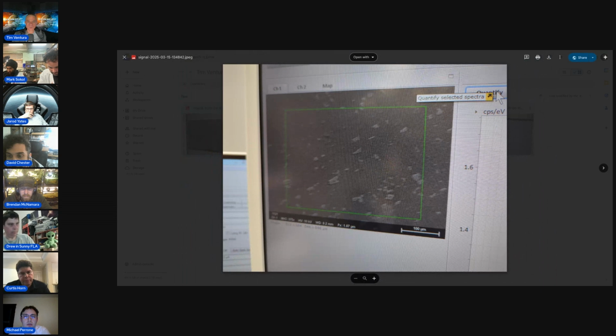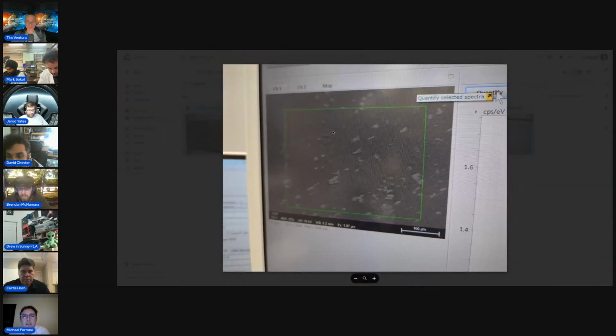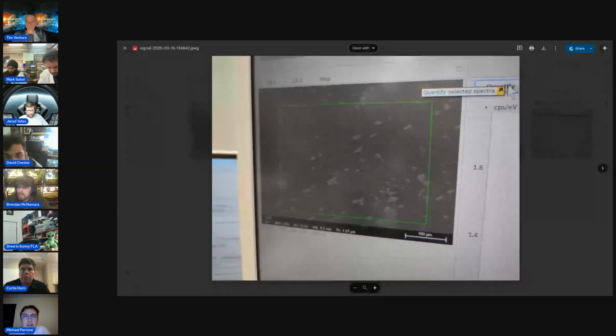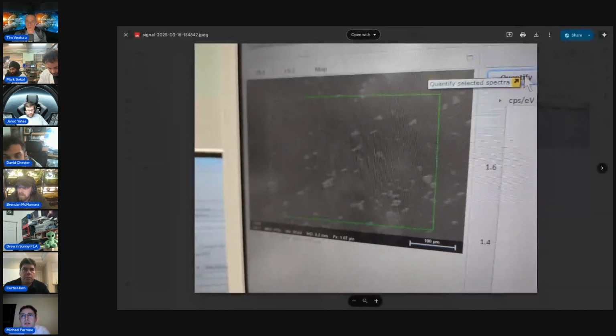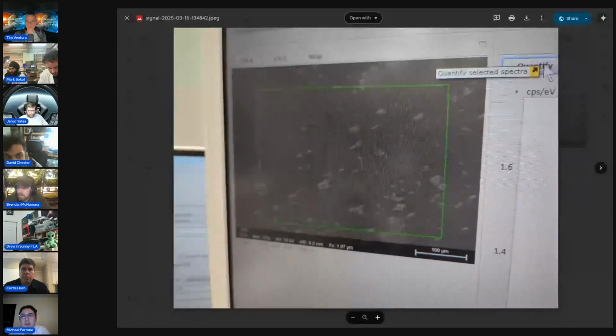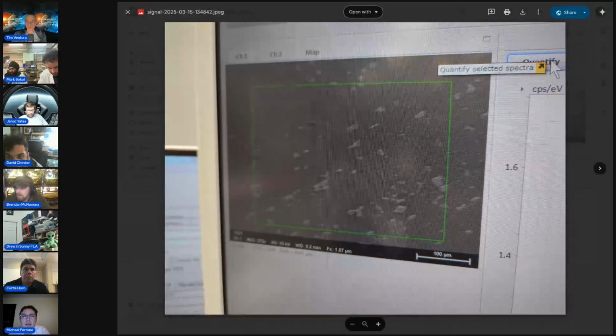But yeah, you can see the microstructure. I was hoping we might see some dendrites, or we etched the surface a little bit here, but we didn't see the grain boundaries as much. Which, for a 7000 series, if you're just using sodium hydroxide, that can happen. The brighter regions seem to have some silicon as well as aluminum, and there may be traces of manganese. And well, we'll get to that. But yeah, this is very preliminary. We'll go back and redo it tomorrow with some sputtering or some other way of anti-staticking the surface.